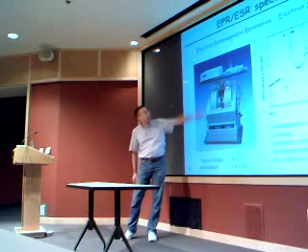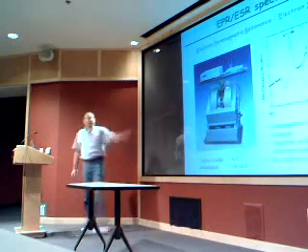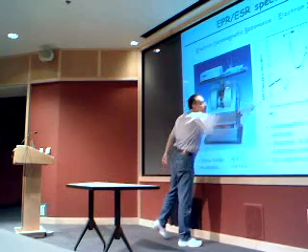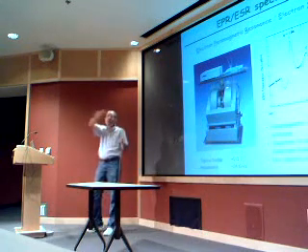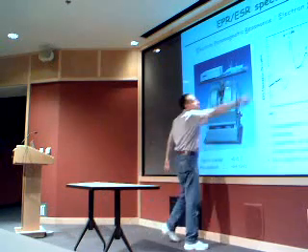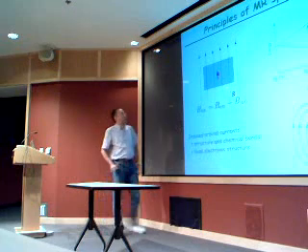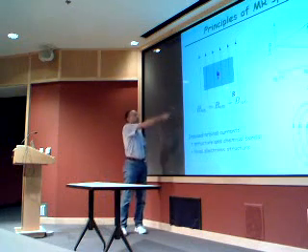So here is an example of an EPR spectrum. Generally, the experimentalists plot the derivative. So this is the magnetic field. This is basically the derivative of the absorption, like we do in NMR. They plot the derivative because by plotting the derivative, you put in evidence a lot of the features. Otherwise, if you plot just the absorption spectrum, you will see just a broad feature with shoulders and so on. By taking the derivative, you get peaks and so on, you put in evidence the structure of the spectrum.